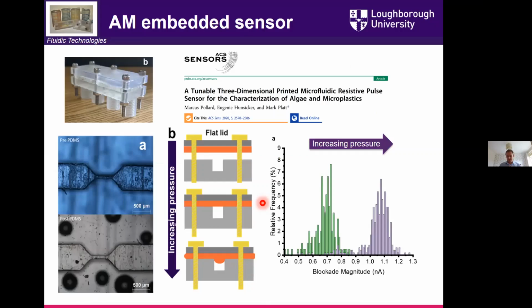We still want to use a simple SLA printer, but we want to try and trick it so we get better resolution. We're still printing the same channels. This is still the same sensing region where the particles are flowing through, and as they pass through that channel, you can characterize them. And it's still about 100 microns in size. We're not printing small features. We wanted to trick the system. Could I assemble components together to get me a better sensitivity?